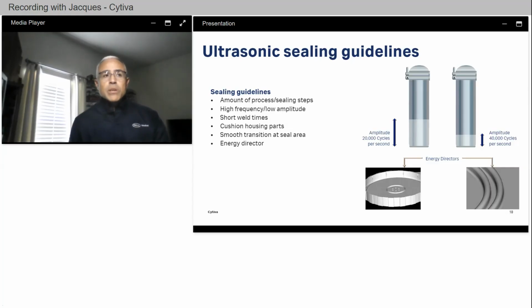Next, when evaluating frequency and amplitude settings, using a high frequency and low amplitude setting is more likely to yield a successful result. We also want to avoid long duration weld times at high amplitudes or gain. Care should be taken to provide a smooth transition from the seal area to the interior surface area of the housing encapsulating the membrane. Also, to maximize transmission of energy that results in a good weld, make sure there's a proper assembly and alignment of the ultrasonic welding tooling within the housing. Otherwise, what can result is an incomplete weld, as well as the risk of increasing stress on the housing and the membrane.